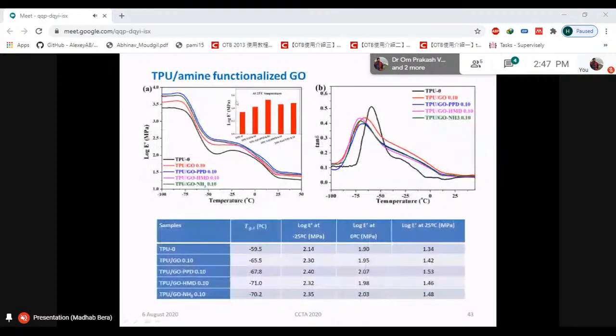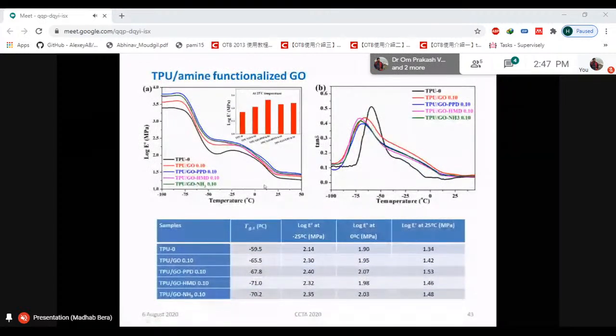And if we see the similar phenomenon for amine functionalized GO and the TPU nanocomposite, then we can also see the effect of the filler is very little in terms of the glass transition temperature. Although for amine functionalized GO the effect is a little bit significant, for unmodified GO, that is only GO, the effect is very little.